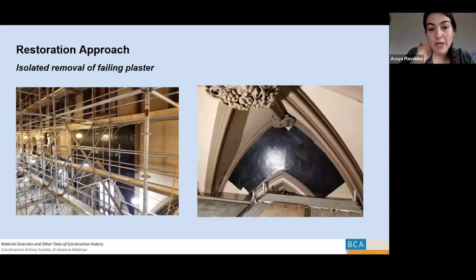One of the challenges that we had during restoration was finding a way to remove that failing layer and any failing finishes without damaging the well-bonded surface. Oftentimes the separating layers were caught under layers of acrylic paint that were sort of hiding what was really going on. So we had to find a way to be conservative about this.